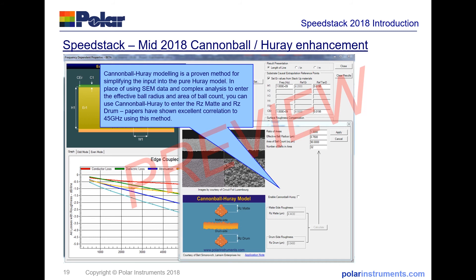Huray modeling of roughness is a proven way to increase the accuracy of roughness modeling over earlier models such as Hammerstad, which are many years old and have stood the test of time well, but are no longer sufficient for current operating frequencies. What's not so easy is to provide the scanning electron microscope information and process that to feed into the dimensional requirements needed for the Huray model. So we worked with Bert Simonovich of Lamsim Enterprises to add the Cannonball Huray model into SpeedStack and SI9000. The Cannonball model allows you to enter a simple RZ mat roughness in micrometers for both the matte side and drum side copper, and those two numbers can automatically generate approximate inputs for the Huray model.